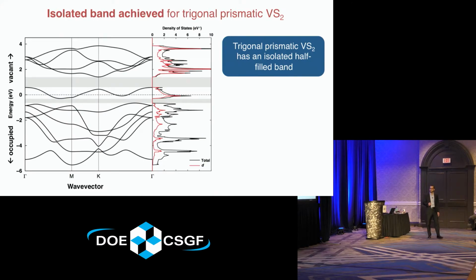So here I can plot, just within density functional theory, the dispersion relation, what's called the band structure for this material. Basically, everything below zero corresponds to occupied electrons, above are unoccupied. And you can see here that indeed we do have this one half-filled isolated level. So that's exactly what we were looking for. You can see there's a gap between it and the sulfur p states below. You can see that there's a gap between it and the other vanadium d states above.